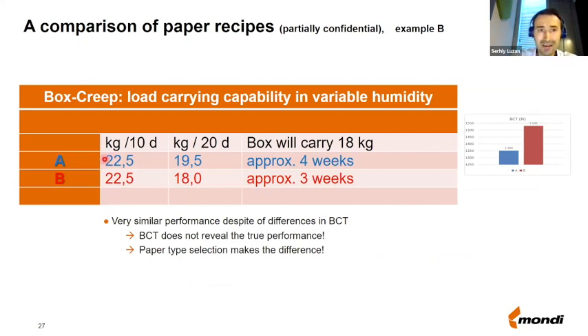We saw that despite different BCT values, the recipe A and B were quite similar when it comes to the load carrying capability. So both recipes could hold 22 kilos for 10 days, 18 to 19 kilos for 20 days. And actually the A recipe could hold 18 kilos even longer, about 4 weeks, compared to B recipe, even though the BCT values for A recipe were lower. So the key message here is that the BCT test itself does not show you the full picture. Your box may have a higher BCT value, but it does not necessarily mean that it will have a longer lifetime in the supply chain.